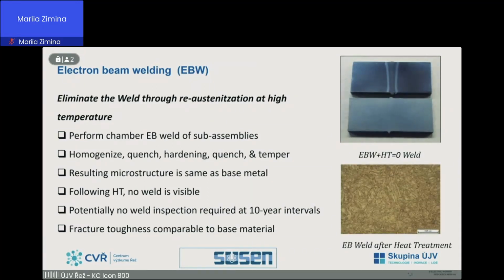The electron beam welding process is extremely efficient, and welding time can be reduced 100 times over conventional thick section welding processes. Post-weld heat treatment effectively recovers the properties in the fusion zone as well as the heat-affected zone. Heat treatment provides properties similar to the base metal properties while eliminating the visual evidence of the weld.